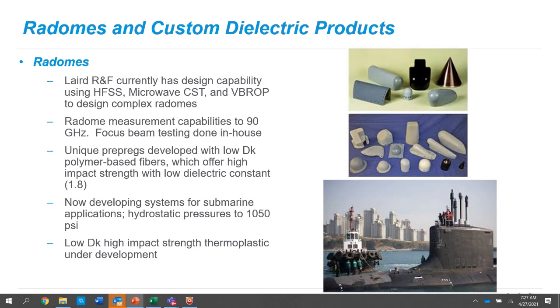So that's what a lot of our work has been done, kind of looking at high frequency, very low dielectric constant Radomes. And then we also do a lot for submarine applications, and so we do have the ability to test for hydrostatic pressures up to 1050. So you don't want, obviously, your Radome to absorb water, because water has a very high dielectric constant, and so the Radome will no longer work properly.